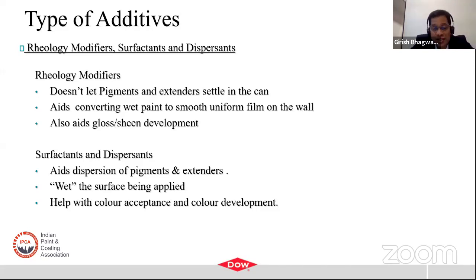So the rheology modifiers also influence the level of gloss or sheen development. By the way, you make a right choice. So it's a very important ingredient. We'll spend a little bit more time on that during the talk. Apart from this, of course, you use surfactants and dispersants, which aid the dispersion of pigments, keeping them separated from each other and not letting them agglomerate. They also help eventually when the paint is applied on the wall, to wet the surface on which the paint is being applied. So the surfactant that we add in paint not only influences the pigments, but it also influences to some extent the surface. So you have to make sure that the surface tension of your paint is lower than that of the wall on which it is being applied. That's important, and it really helps with color acceptance and color development.